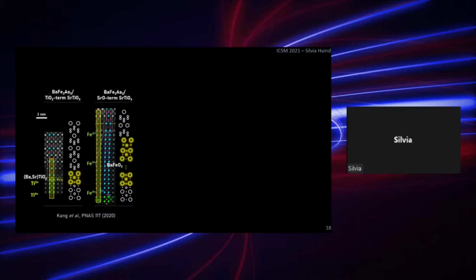As you can see, several unit cells are thick, and this is because we have here a valence change of the iron. Going from the top, close to the barium iron 2 arsenic 2, down to the bottom, we see the valence change from 2+ over 3+ to 4+.